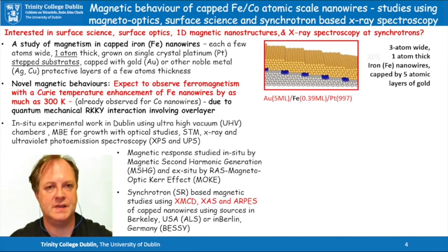What do we expect to see? We have an expectation that these will exhibit very novel magnetic behaviors. We expect to observe a peculiar variety of ferromagnetism with a Curie temperature enhancement of these iron nanowires by as much as 200 to 300 Kelvin. We've already observed this for cobalt nanowires, and this is due to a quantum mechanical coupling called the RKKY interaction involving the conduction band electrons in the gold overlayer.